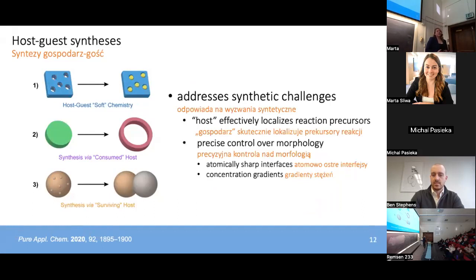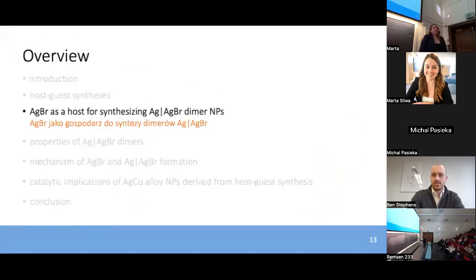So host-guest techniques address a lot of the synthetic challenges that I just mentioned a few slides ago, and one of the most outstanding ways in which host-guest chemistry helps address these challenges is by localizing those reaction precursors to a very small nanoscale volume, which then gives you the potential to create atomically precise interfaces between those building blocks, and also allows you to exploit concentration gradients that are not mirrored in the bulk on larger length scales in these materials.